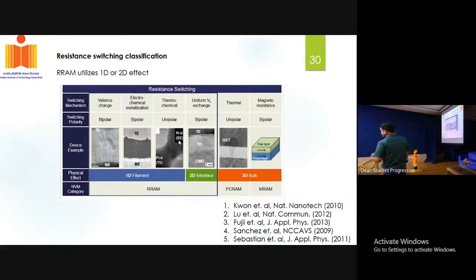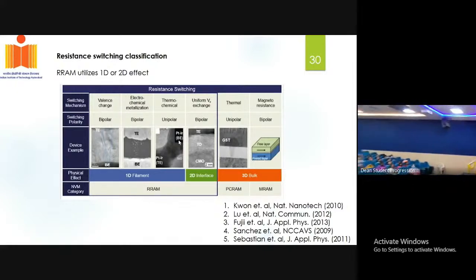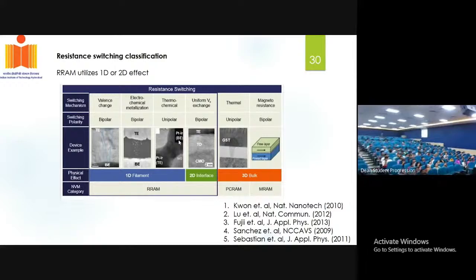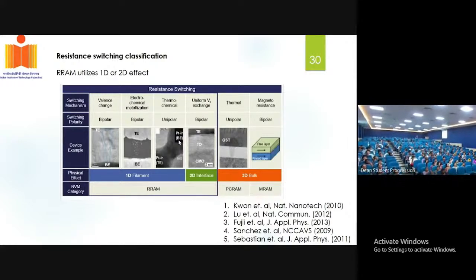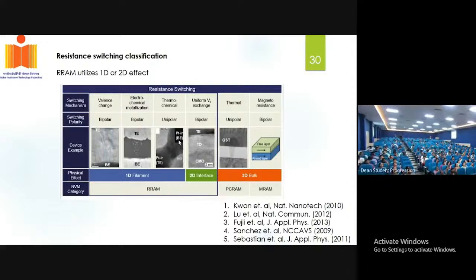So basically, if you look at the resistive random access memory, it works based upon a one-dimensional conducting channel. Because of the oxygen defects, these channels form. In the case of MRAM, you will have a 3D bulk effect. You essentially measure the magnetoresistance of the device.